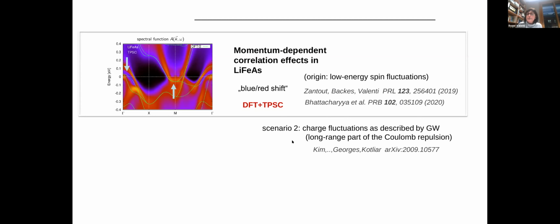I should mention also that very recently, Kim, Antoine Georges, Gabi Kotliar, and collaborators did a different kind of calculation. They did basically GW plus what they call extended DMFT, so that they are including all contributions of the long-range part of the Coulomb repulsion. And by doing this type of approach, they seem also to be able to explain this type of features. So here, I think this would be an interesting subject for discussion. One scenario, which is the scenario I am presenting, is more describing this type of effects in terms of the low energy spin fluctuations, while scenario 2 is describing this type of effects in terms of the long range part of the Coulomb repulsion. So this, I leave it as an open discussion.